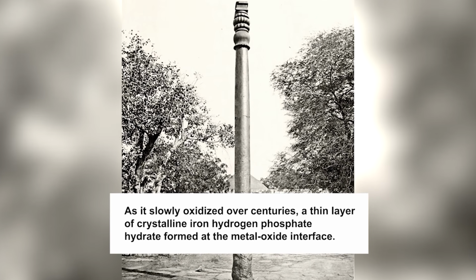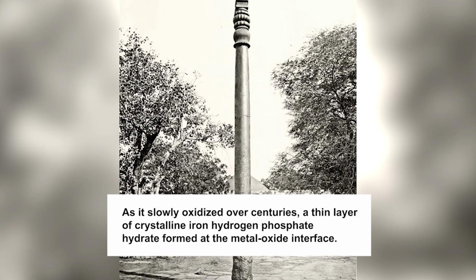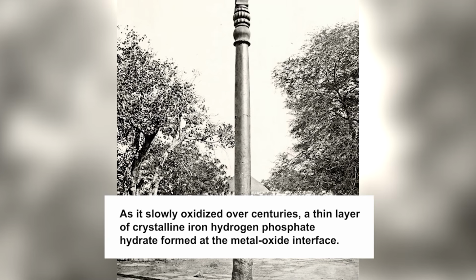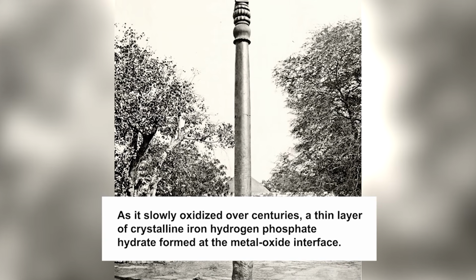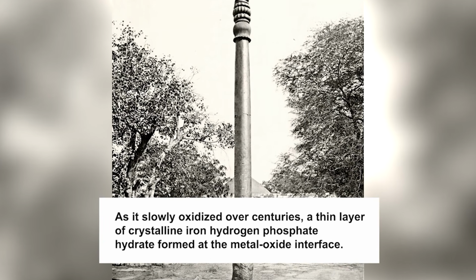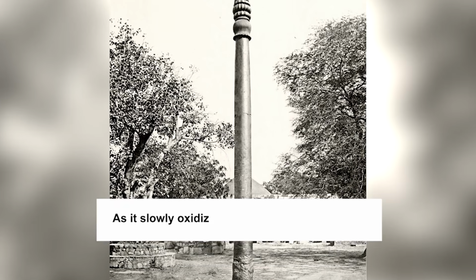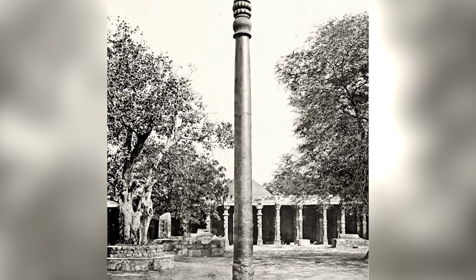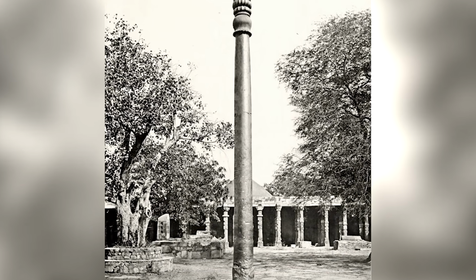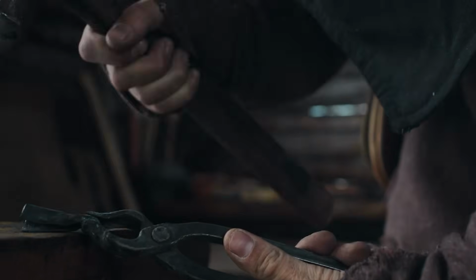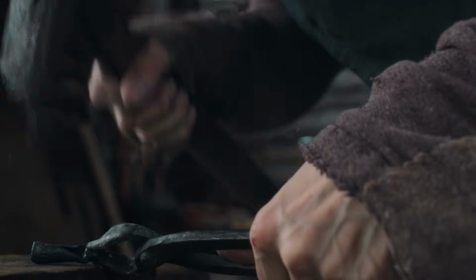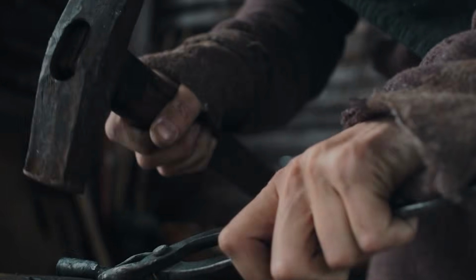As it slowly oxidized over centuries, a thin layer of crystalline iron hydrogen phosphate hydrate formed at the metal oxide interface. This layer is incredibly stable and non-porous. It functions like a ceramic coating. Moisture cannot penetrate it. The pillar stopped rusting after forming this protective skin. Medieval European smiths were creating the same effect on a smaller scale. Every time they forged a tool from phosphorus-rich bog iron.